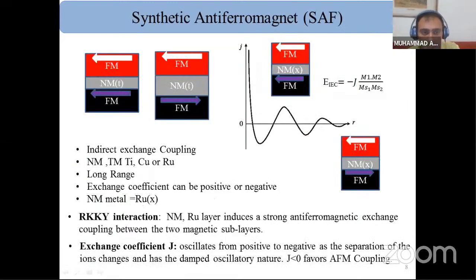Synthetic antiferromagnets are a tri-layer system in which two ferromagnets are separated by a non-magnetic ruthenium metal, and the interaction between the two ferromagnets can be mediated with the help of ruthenium. This kind of interaction is long range. Depending upon the thickness of the ruthenium metal, this interaction can be ferromagnetic or anti-ferromagnetic.